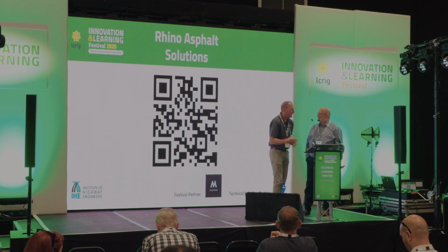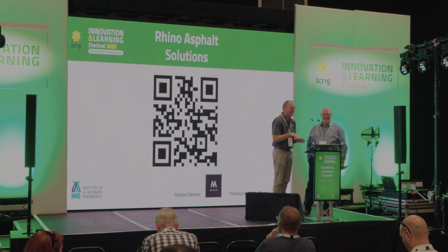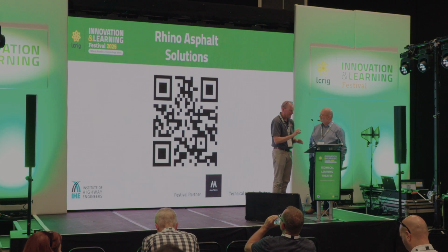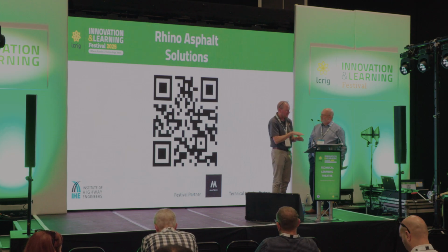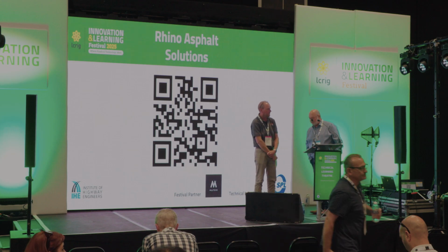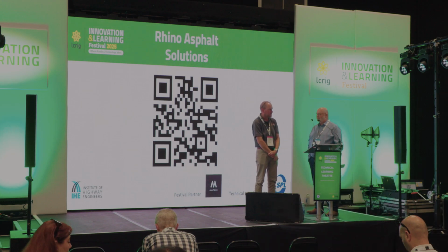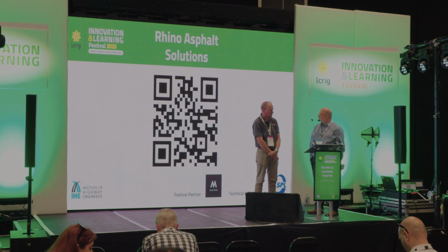We've got just a few minutes, so it's an interesting discussion. My observation of the modern materials is that they fret and they fail in a different way than the old traditional asphalts. I'm interested in that application about sealing that surface at the early stage. Yes, certainly with things like SMAs, there's a tendency for them to fret and ravel, which is why we see a lot more of the surface lane joint deterioration on roundabouts. Certainly the surface applied materials are very resilient and will withstand a lot of traffic, on things like roundabouts and areas where there's a lot of friction.